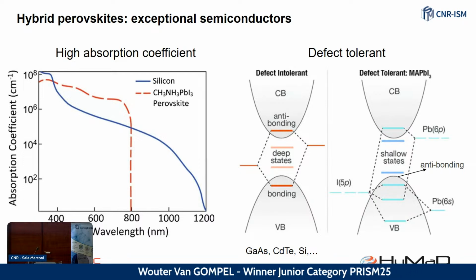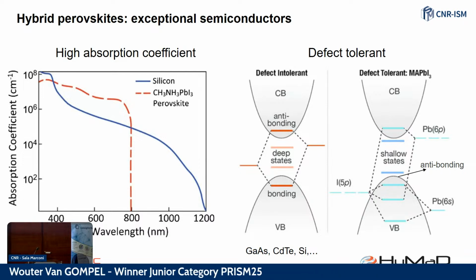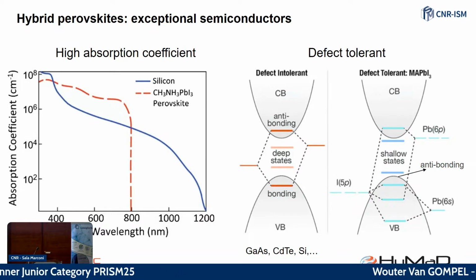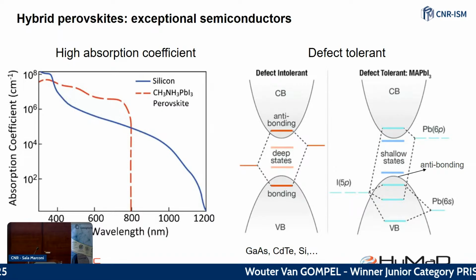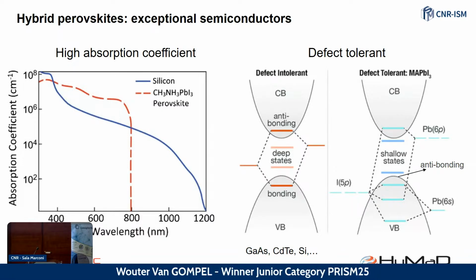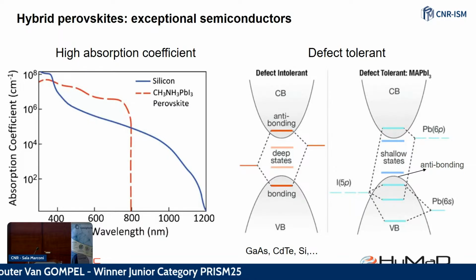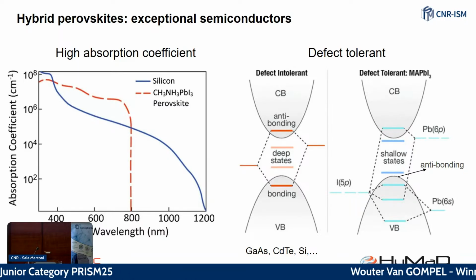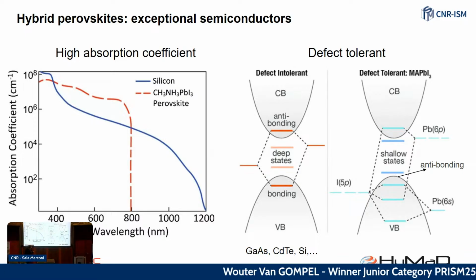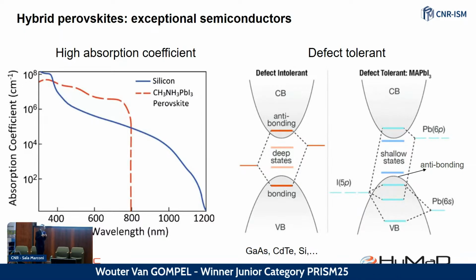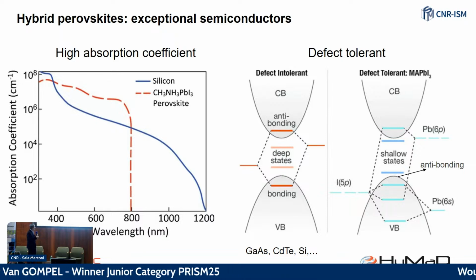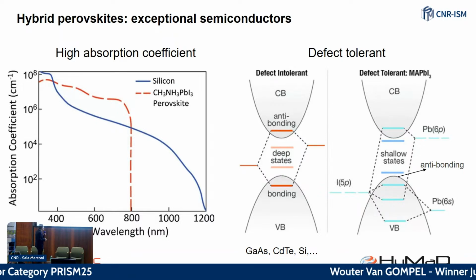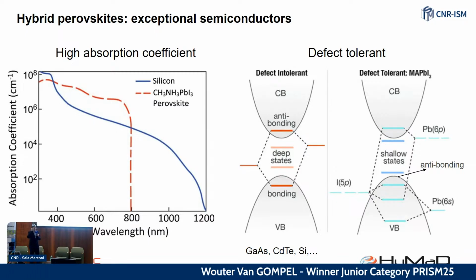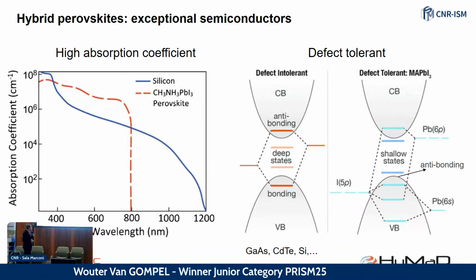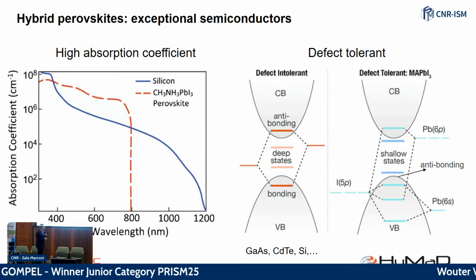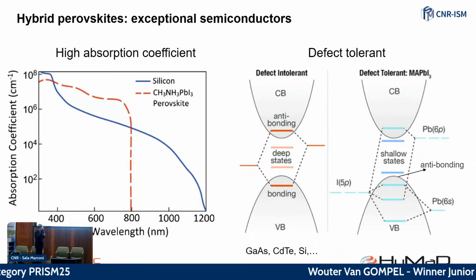Then another very important point is the defect tolerance, which is maybe even more important. So why do we say that these materials are defect tolerant? When you compare them to the classical semiconductors like gallium arsenide, cadmium telluride, silicon, and you look at this very simplified band structure, you see that the atomic states are actually located inside of the band gap, which means that if you get defects like vacancies, you will get deep trap states. And of course, because they are deep traps, they are not easily detrapped, so they really act as trap states for the electrons, and they also have a quite high scattering cross-section for electrons, which is not what you want.